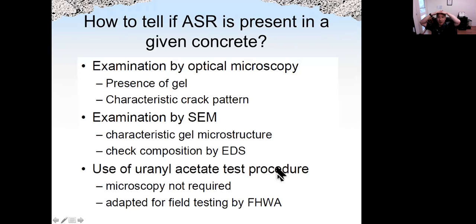Okay. So how to tell if ASR is present in a given concrete? There are different types of methods. We can use an optical microscope to see if we have a gel, as in the sample picture shown moments ago. We can also observe the pattern of the crack. If we see map cracking on the surface of concrete, and also see whitish gel coming out of the crack, very likely it's caused by ASR.